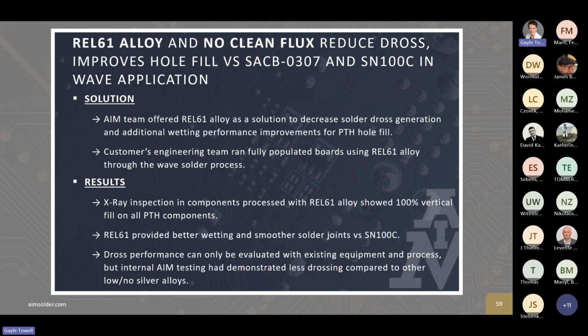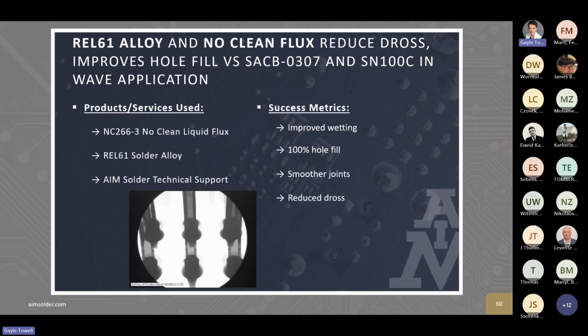The end result was X-ray inspection and components processed with REL61 had 100% vertical hole fill, and it provided better wetting, smoother solder joints compared to the SN100C, and dross performance. I'm not sure if it was fully quantified in this application, but they did see less dross compared to the other alternatives. So again, they saw improved wetting, 100% hole fill, smoother joints, and reduced dross by switching to REL61.